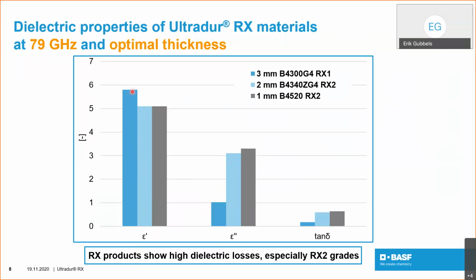However, it is interesting to note, as I mentioned before, the dielectric permittivity and loss cannot be tuned independently of one another. However, we were able to reduce the dielectric permittivity, but significantly increase the dielectric losses, making the absorbers a material which reflects not too much radiation, but absorbs most of it, which is also addressed by the tangens delta, which is nothing more than the quotient between the dielectric loss and the dielectric permittivity.